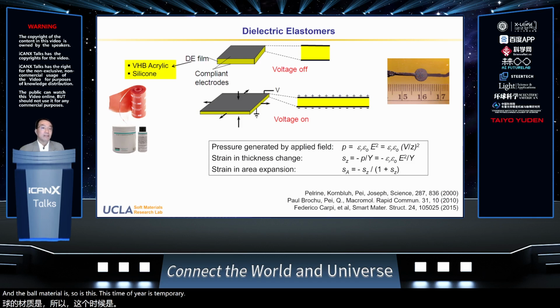So the dark color you see there is carbon grease applied on the surface as the compliant electrode. When you apply a voltage on, you will see that the film gets squeezed, its area expands. When the voltage is removed, the film contracts. So voltage on, off, you see the film repeatedly expand and contract.